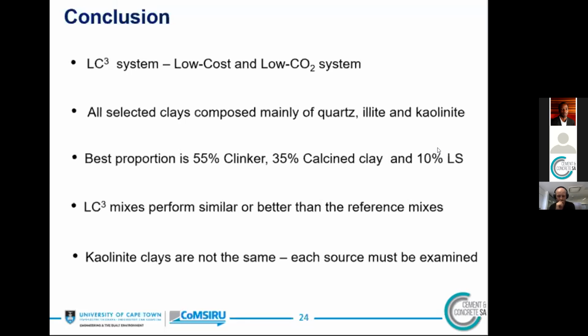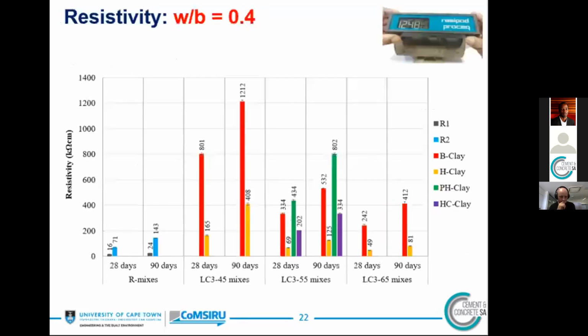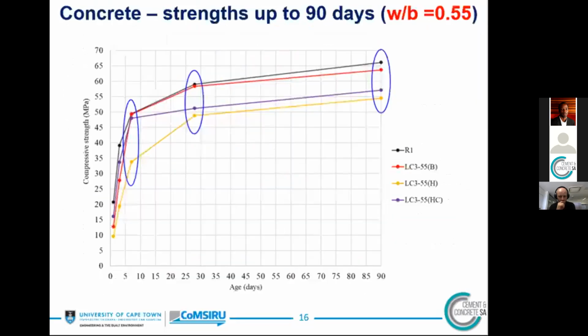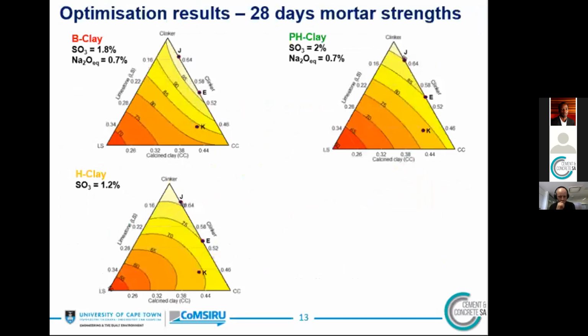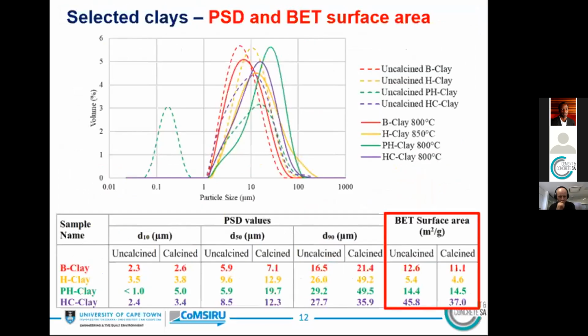I also saw that if you looked at the H clay, I think in slide number 12, it was calcined at 850 degrees Celsius as opposed to the other ones. Why was this the case? This clay we received already calcined by the supplier, from Cowling Group. So we had to use it directly. But they also gave us a small sample of uncalcined clay, and we calcined it at 800 when we tried to check the activity. The activity was almost the same. Okay.